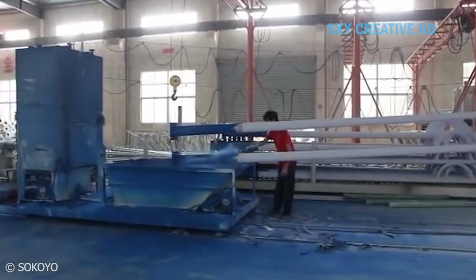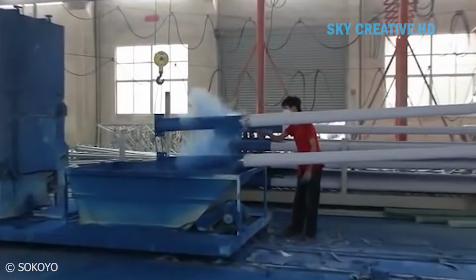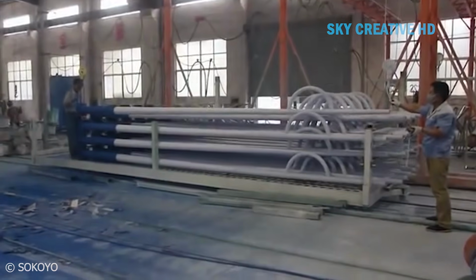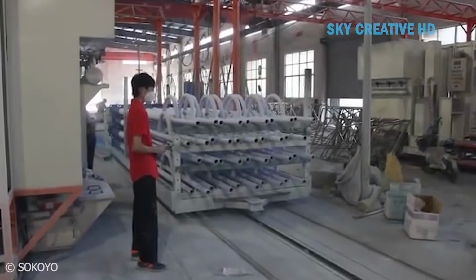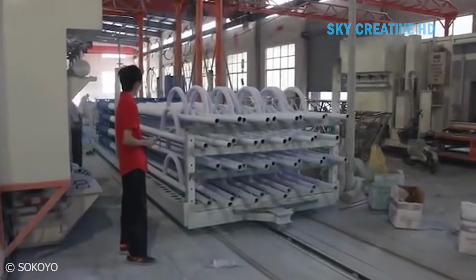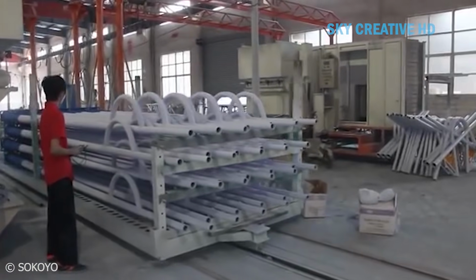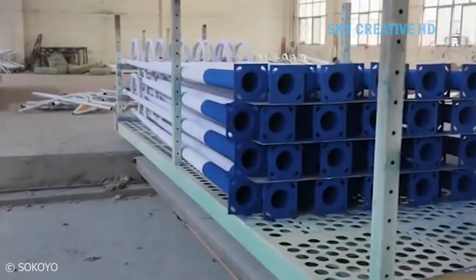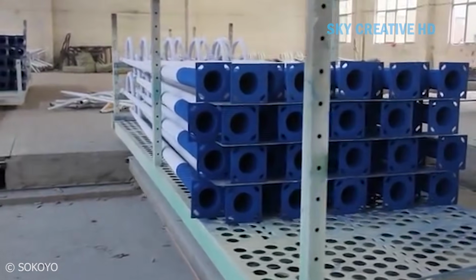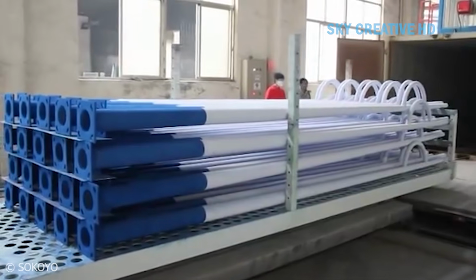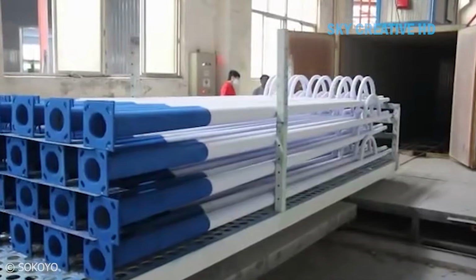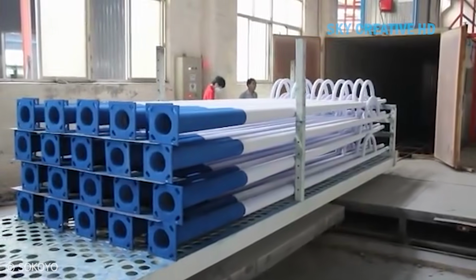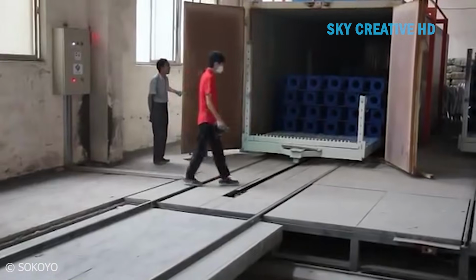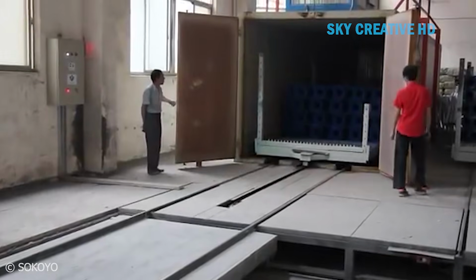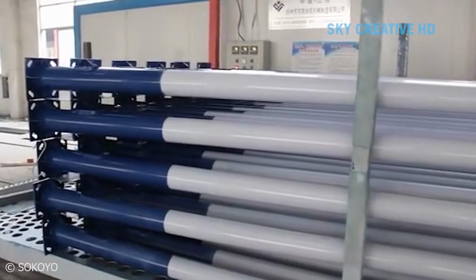From fabrication, the poles move to surface treatment, and this is where longevity is really determined. The standard process for road-grade streetlight poles is hot-dip galvanizing. The entire pole assembly is immersed in a bath of molten zinc at around 840 degrees Fahrenheit, 450 degrees Celsius. The zinc reacts metallurgically with the steel surface, forming a series of iron-zinc alloy layers, topped by a pure zinc outer coating. This galvanized coating is sacrificial. It corrodes preferentially to protect the underlying steel. And when properly applied, it provides corrosion protection for 50 years or more in typical outdoor environments.